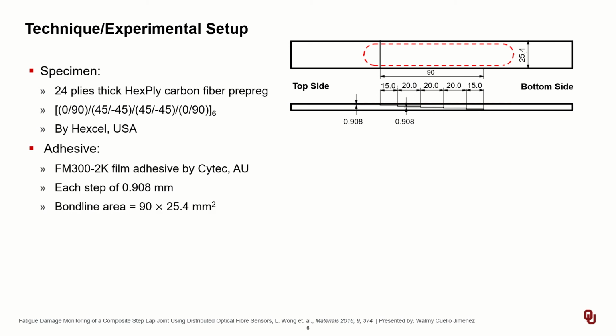The adhesive used was FM300-2K by Cytec in Australia. Each step of the lap joints has a thickness of 0.908 millimeters, and the bond line area, as per the schematic, is 90 by 25.4 square millimeters. The fibers were bonded onto the top surface of the specimens following the red dotted line pattern with Loctite 406